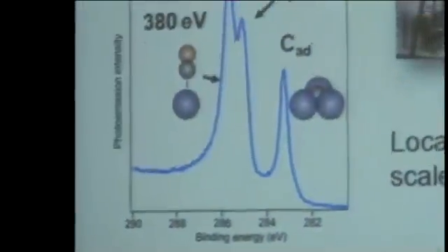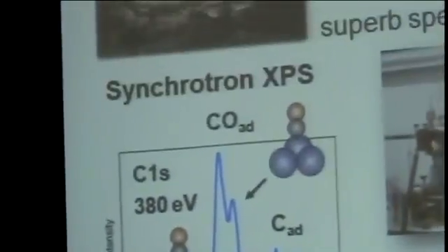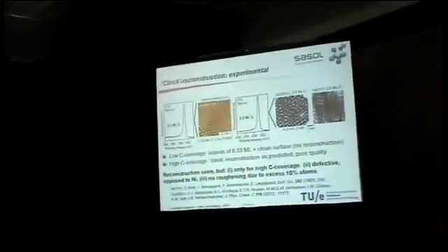I'm a surface scientist, so I took an experimental approach using a flat single crystal surface, a close-packed surface of cobalt, and we used a combination of synchrotron XPS, which provides the chemical nature of the adsorbate, and in particular the chemical nature of the surface carbon, and combined that with STM, which gives us an image of the local surface structure, but doesn't really have the direct chemical information. So the two together can help us to understand the rich surface chemistry of carbon and cobalt.